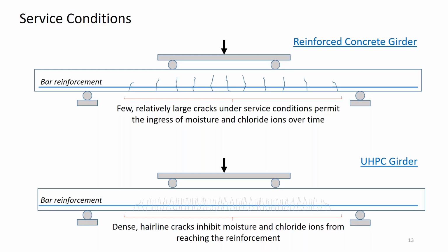And if you remember in undergrad school, when we took reinforced concrete design, we know that concrete is cracked. You have a number of large cracks under service conditions. We were always told that is okay, and that's certainly okay. But of course, they're large enough that we do have ingress of moisture and chloride ions, as you can tell from many of the bridges you drive under. However, UHPC does have bar reinforcement. Some people might think that it doesn't, but you do need bar reinforcement. But the difference is that because of its cracking process, you have a dense hairline set of cracks that are so fine that they inhibit moisture and chloride ions from reaching the reinforcement. And that is one of the big benefits of building with UHPC. In a way, I almost think of it like a pre-stressed concrete member, although of course it's not. And you can pre-stress UHPC members too.